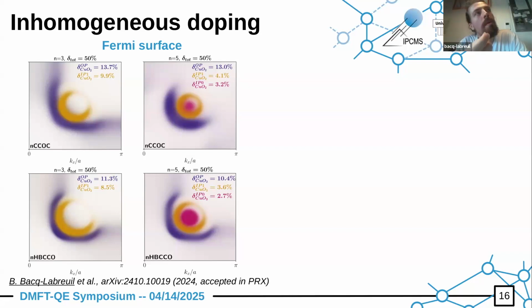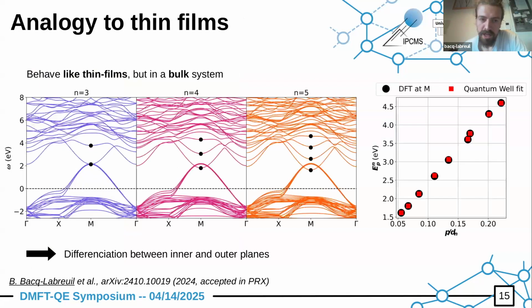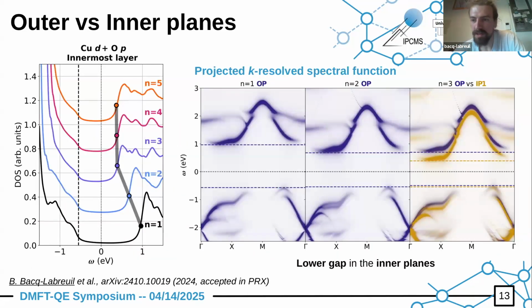Yeah, I mean, the correlations are weaker. You can see here that the difference between the outer planes and inner planes is a few hundreds of millielectron volts. So it's not a drastic decrease of the correlations. So it's slightly less correlated, but still enough that you would open a gap and get a pseudo gap in the underdoped regime. Yeah, as far as I could tell now.